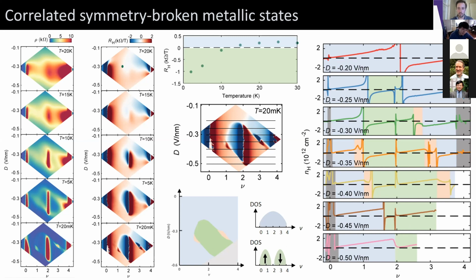I think that actually indicates that the system is even more strongly correlated than twisted double bilayer graphene. In that picture, there's work from Shahal Ilani's group and also Ali Yazdani's, where they do spectroscopic probes. What they find is this cascade of symmetry breakings, where effectively you can think of having these 4 degenerate Dirac cones. When you start filling from neutrality, you start putting charge into all 4 equally. But once you get to quarter filling, one of them fills all the way and it sucks the charge out of the other 3. Then your chemical potential is effectively back at the neutrality point for those first 3 Dirac cones. The 4th one is filled. So the Hall density in that case doesn't actually change sign. It just resets to 0. I think that's a consequence of correlations being even stronger, because then you're spontaneously filling an entire band rather than just creating a small gap between them.